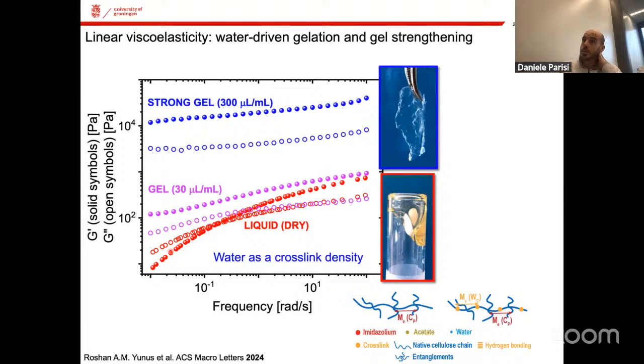Okay. As soon as we start adding a little bit of water, you see that for the whole frequency range explored, G prime is always higher than G double prime. So we got what we called an arrested state, or the system gets dynamically arrested.